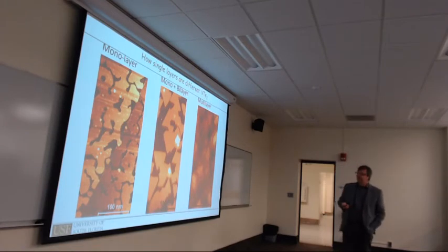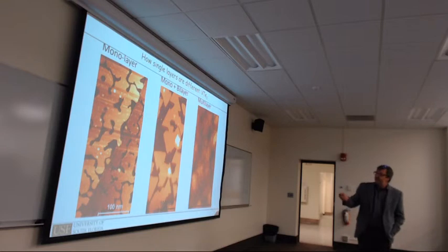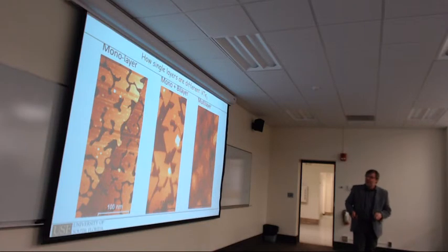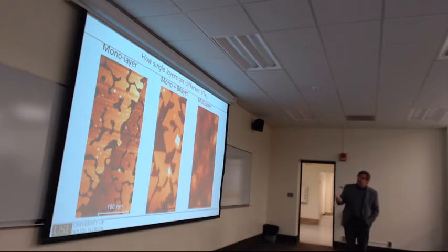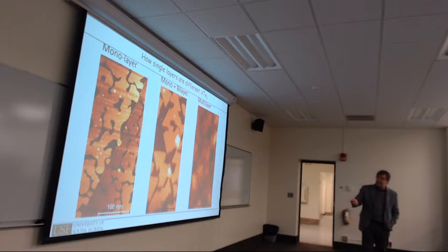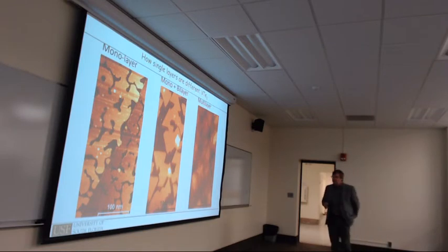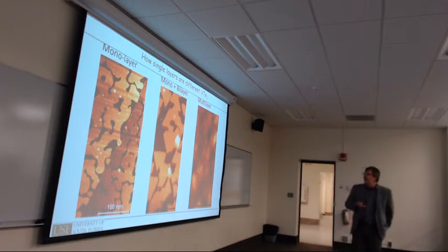So to study that, again, we have to grow this material first. So we grow vanadium ditelluride, different layers, so that this is a monolayer structure. I think this is grown on graphite, so this line that goes through here is just a step on the graphite substrate, and then you have monolayer islands kind of merged together. If you grow the bilayers, for some reason the step edges become much better pronounced. So you have a bilayer structure on top of a monolayer, and then you can grow thicker films, and you can see the film starts to roughen, so you get many layers exposed, and you get these different terraces. But the main point is that we can grow from monolayer to multilayer fairly well defined ditelluride.